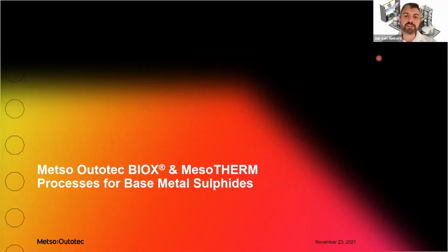Yeah, Ken, you'll have to determine that for every concentrate. As I said, it's both the sulfur mineralogy as well as the carbonate concentration that will determine whether the concentrate is acid producing or acid consuming. Now, normally you don't really have much control over that in the process, because you have to treat the concentrate that you're given. But we do see that most concentrates are acid producing, so requiring lime or limestone to neutralize or maintain the pH.